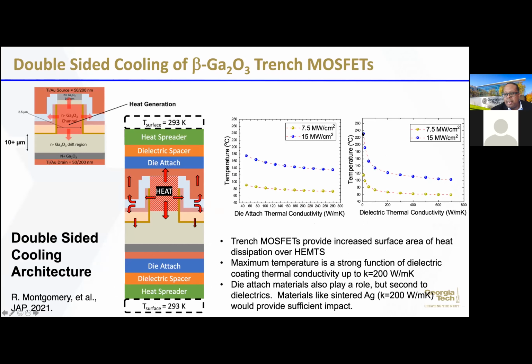benefit. So you see most of our dielectric materials are down around 1 to 2 watts per meter K. If I can create dielectric materials that even have a slight increase in thermal conductivity, you're going to see this temperature begin to drop quite a bit. And so again, for these trench MOSFETs or these FinFET structures, this is where a lot of the action is in terms of where do we go.